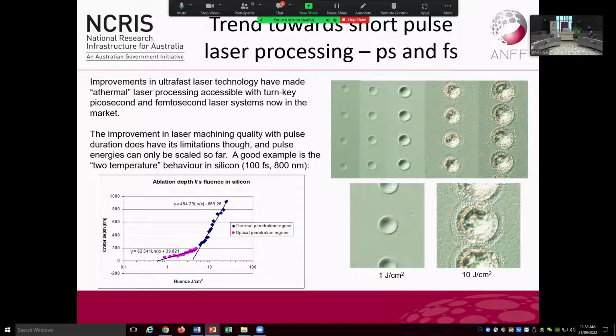There's only so far you can push these processes. Just because you have a femtosecond laser doesn't mean you can process something with a femtosecond laser in hundreds of microjoules. At some point you'll still be putting so much energy into the system that you will get molten effects. And I just have an example here from my work when I was looking at this, where we were just looking at everyone's favourite substrate, silicon, and seeing what happened as we started to push the pulse energy up and up and up.